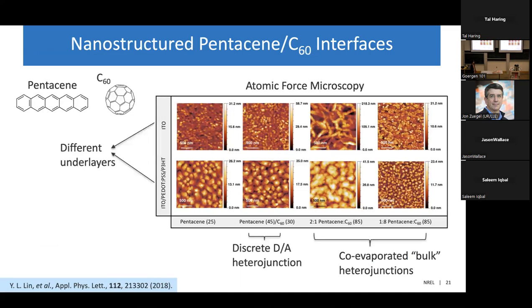In addition to rubrene, we did some systematic studies on another singlet fission material called pentacene. So it's a linear acene with 5 rings. And we looked at different underlayers. So we used plain indium tin oxide as our substrate, as well as ITO that had been coated with PEDOT:PSS or P3HT, which is a very common hole extraction material in these solar cells.